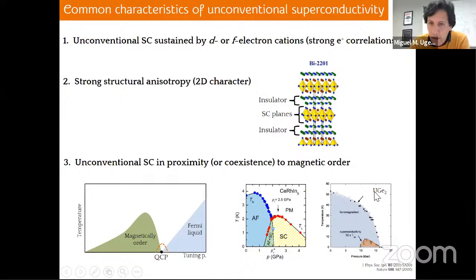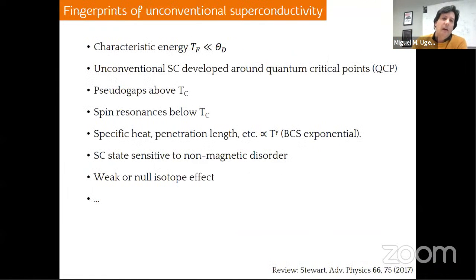And for this uranium-based heavy fermion compound, the superconducting dome is actually not overlapping, but inside the ferromagnetic phase. So both phenomena are coexisting actually. Okay, so there is a long list of typical fingerprints that can be